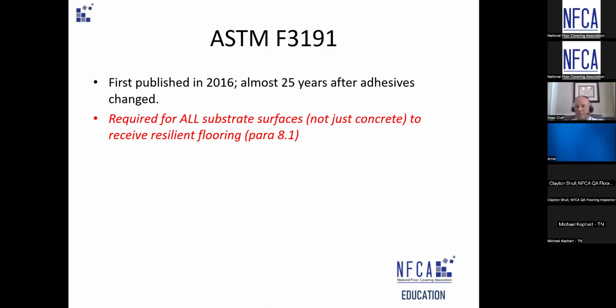Well, guess what? That's not your new substrate. You still got to do the porosity test. Because the idea is, well, I skimmed it, it's porous. Maybe, maybe not. Do the water drop test. It's quick. And we did this on a project in Lakeland in Central Florida. They're like, oh, we skimmed it, it's porous. Did you do the water drop test? 12 people standing around, architect, owner's rep, GC, flooring contractors did a water drop test.